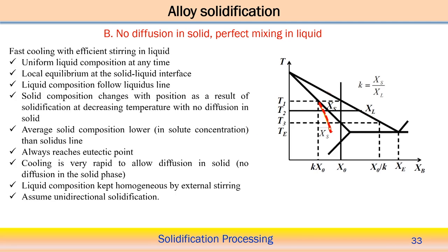Now, similarly, k equals Xs by XL, and we are seeing this, but the only difference is that the solidus line is actually following this way, the dotted line in red color, because we are not allowing diffusion to occur. But of course, some sort of diffusion is occurring over time. So, it is not always keeping the kX0 concentration; rather, the solute concentration in the solid phase lies between the solidus and kX0.